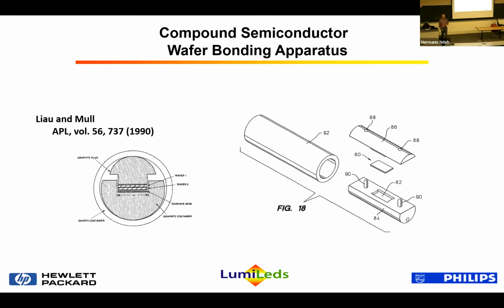The first work that was done on this was by Liau and Mull out of Lincoln Labs. What they came up with was an apparatus where you have two pieces of graphite and you put the two wafers in between them, and you put that in a quartz cylinder. Then because of the differential in the thermal expansion coefficients of graphite and quartz, you could apply uniaxial force to the wafers. The problem with this is it was very hard to control when you actually applied force, how much force you applied, and at what temperature you applied it. But nevertheless, they were able to fuse indium phosphide and gallium arsenide together, and they reported that in 1990.